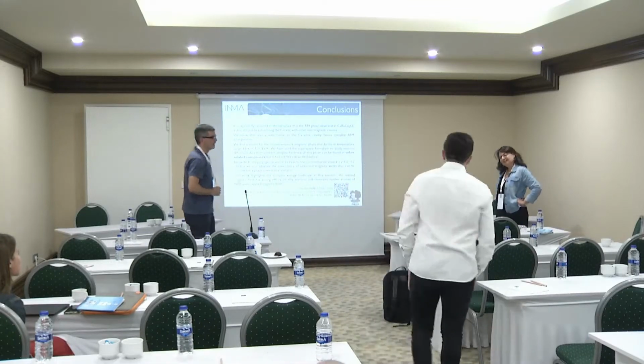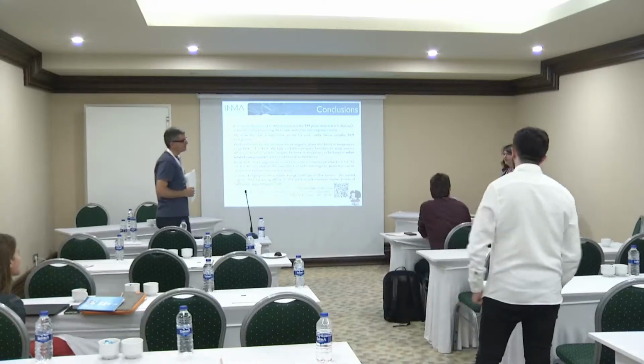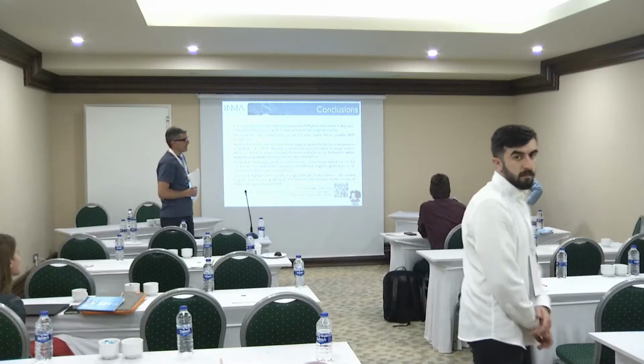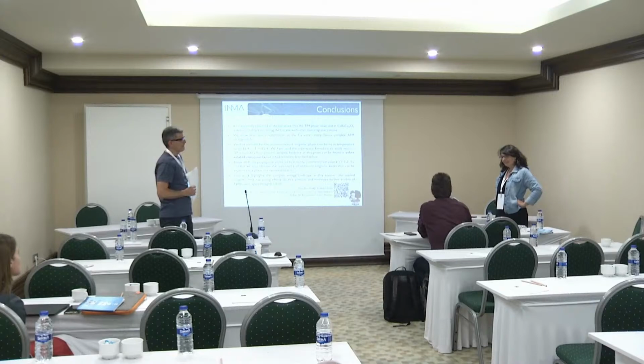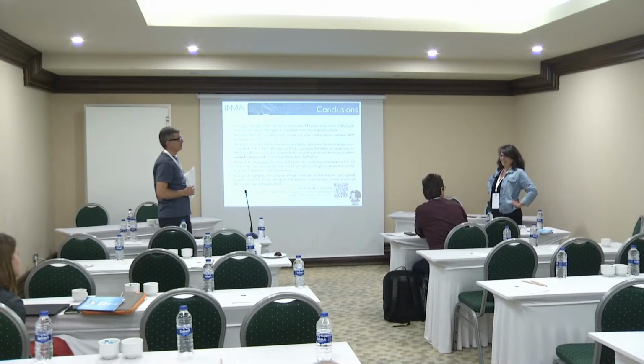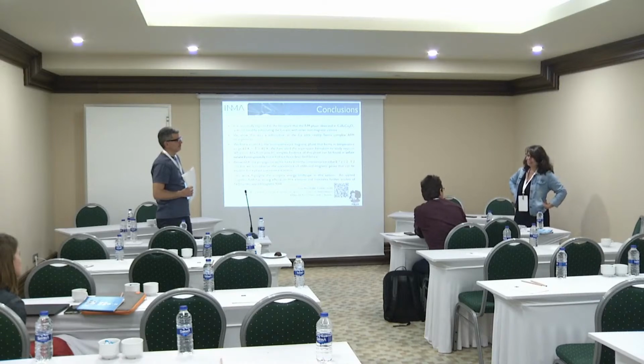So these are very frustrated layers. You said also that interlayer coupling is relevant. So for the Kagome, I wouldn't even know what kind of order I would expect, but for the triangular, I would expect this 120 degrees ordering. But that would be 1/3, 1/3, 0, right? Yes, and that doesn't... Do you have any understanding why you get another ordering wave vector?